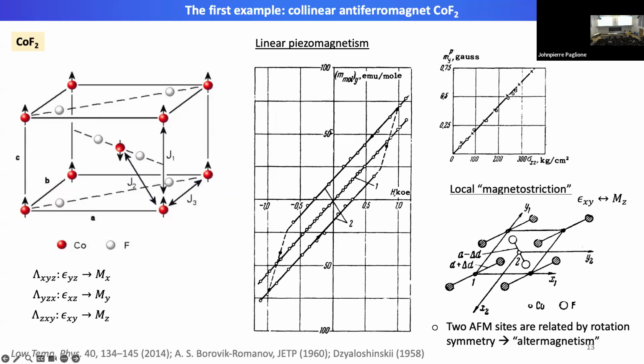So here, this is the induced net moment as a function of the applied stress. I think the unit here is in the unit of stress, but it would be on the order of 0.1%. You can convert it to Pascal. Okay, so you can see that there's a linear dependence of the induced moment as a